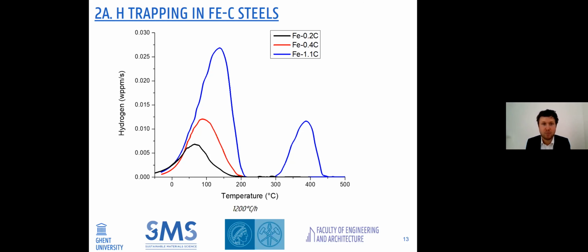You can see for the 1.1 carbon steel in blue that we have a quite high temperature peak. This is linked to the presence of retained austenite, as you remember from the previous slide. This retained austenite contained hydrogen and released its hydrogen upon heating. This is not detrapping from austenite. This is actually the phase that was decomposed because of the temperature that was applied.